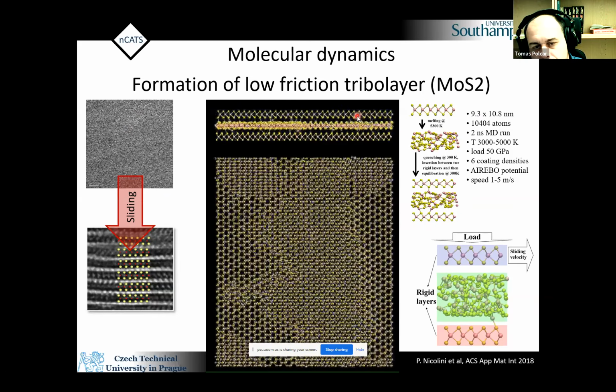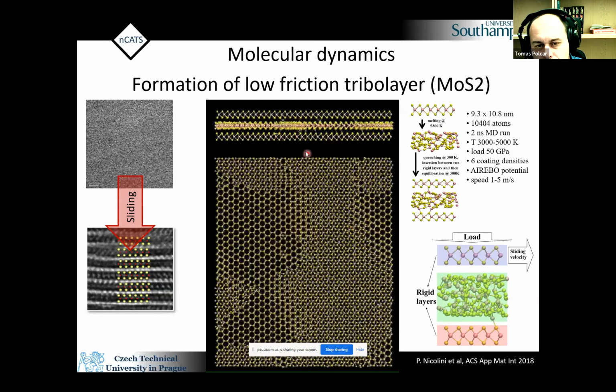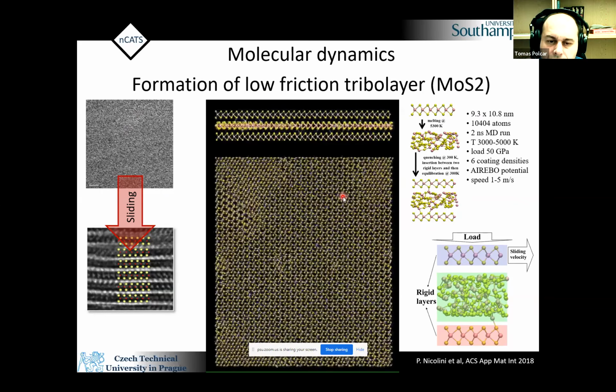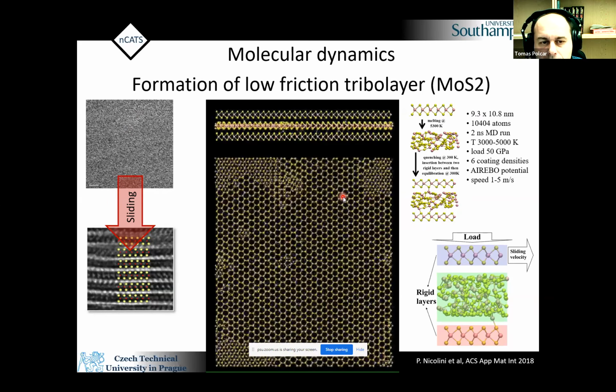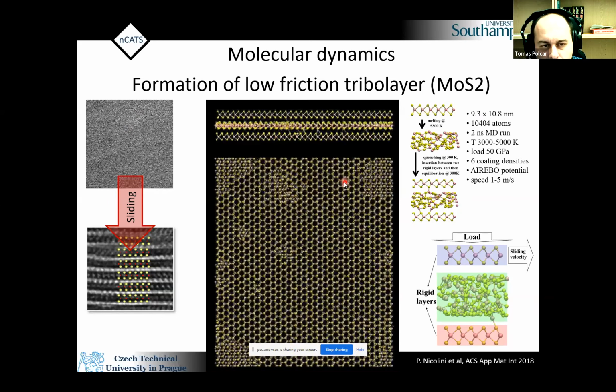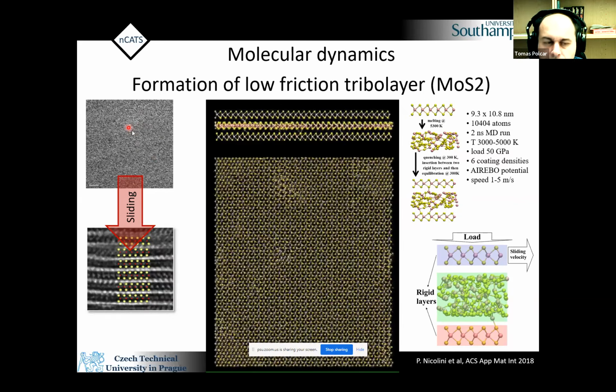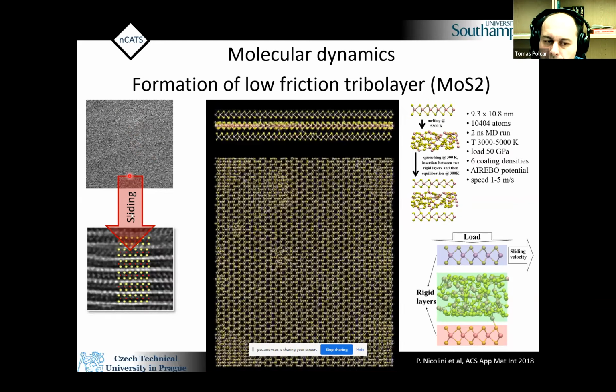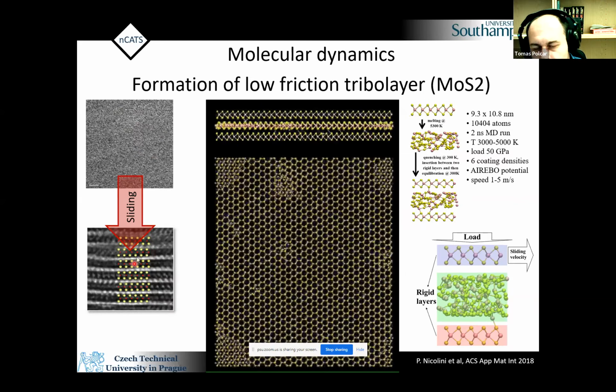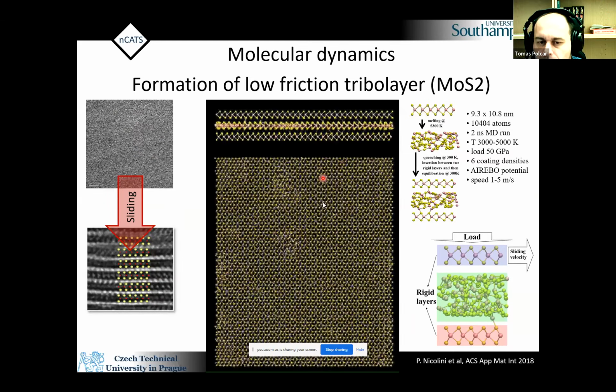And always what we ended up with was a very nice, relatively fast crystallization of the material. This is the experiment where you have amorphous material with molybdenum disulfide, we slide it, and this is what happened on the surface. And our simulation shows something similar.